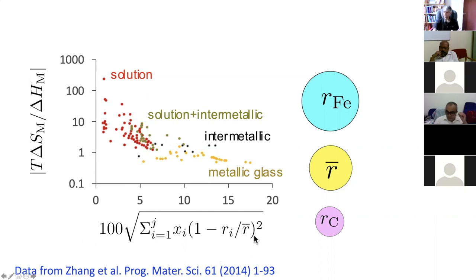And the Cantor alloys that I illustrated earlier have very little misfit, because chromium, iron, manganese, and so forth, have very similar atomic radii. And there is a really interesting piece of work done by Nick Jones and Howard Stone, where they compared the level of lattice strain, that means not a homogeneous strain. We all know that when we add a solute to a solvent, the lattice parameter increases, but that's not a heterogeneous strain. It's a homogeneous strain where the lattice parameter expands.